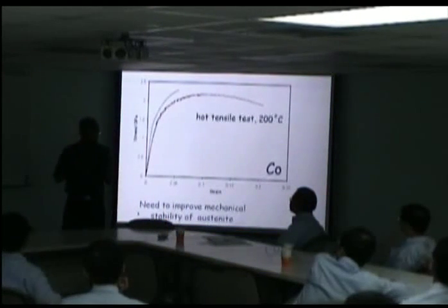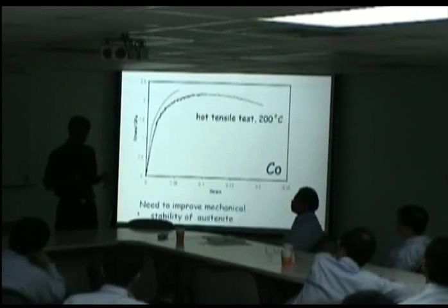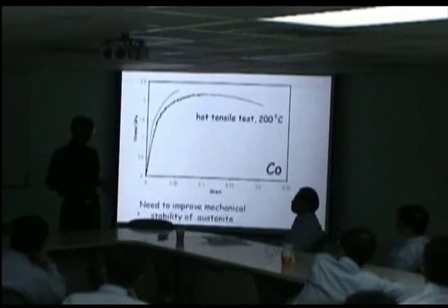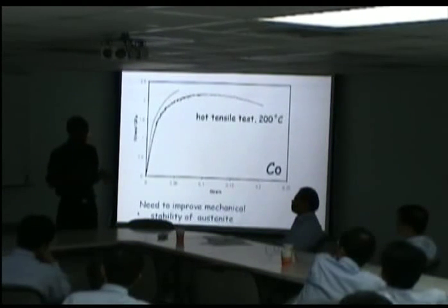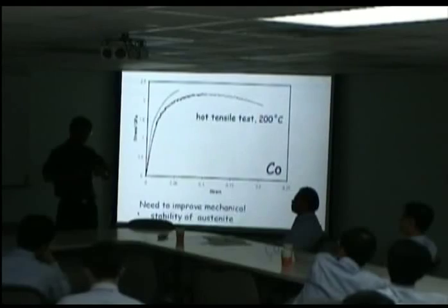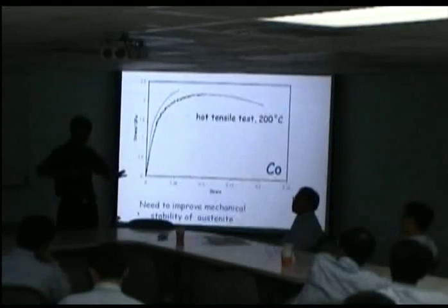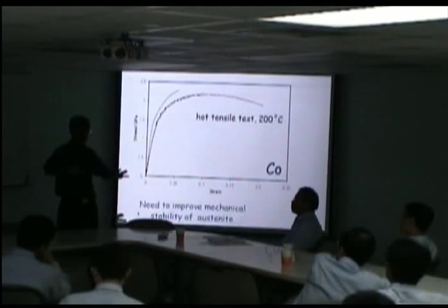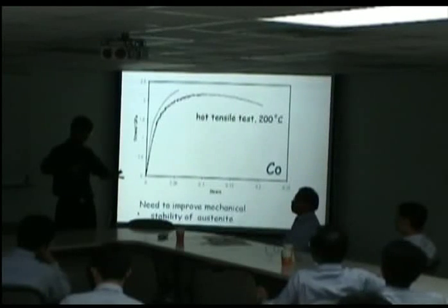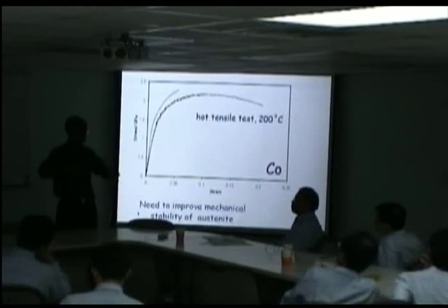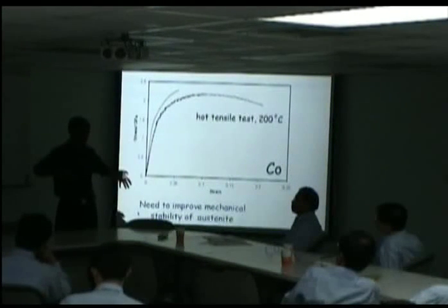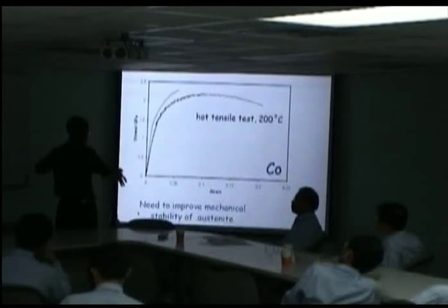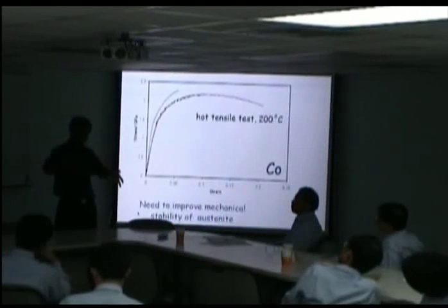Now, all of that can be put into a composite model. There's such a lot of work on composites. The models exist, and what they show is that you have inhomogeneous deformation. At first, when you apply the stress, nothing happens to the hard phase. In this case, it's a mixture of bainite and austenite. It remains elastic, and the plasticity is being absorbed by the ferrite. It's only when the ferrite has work hardened that the harder phase starts to deform.